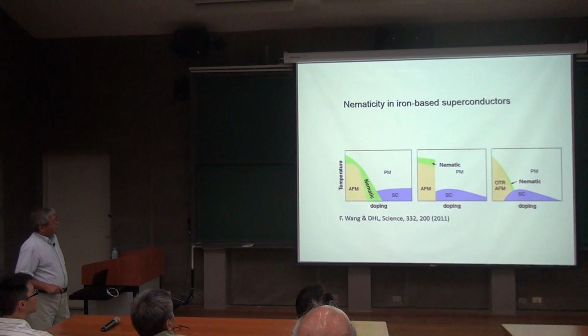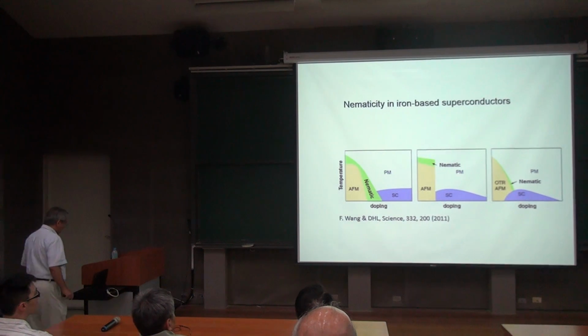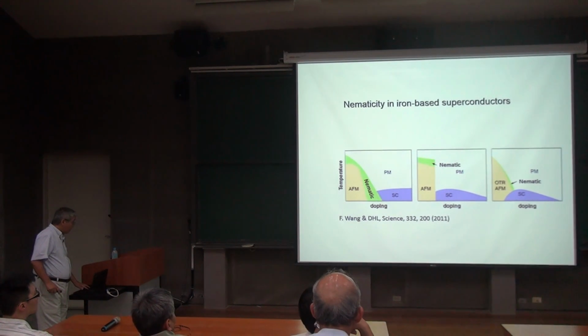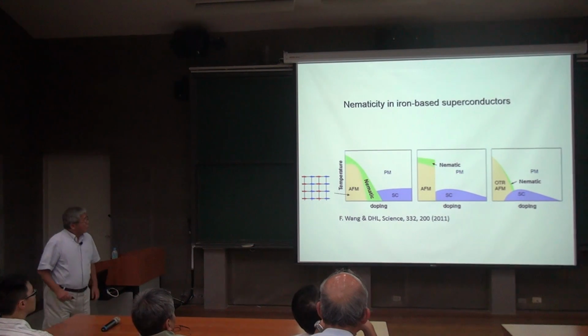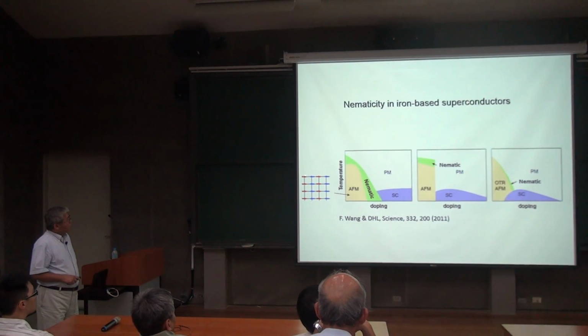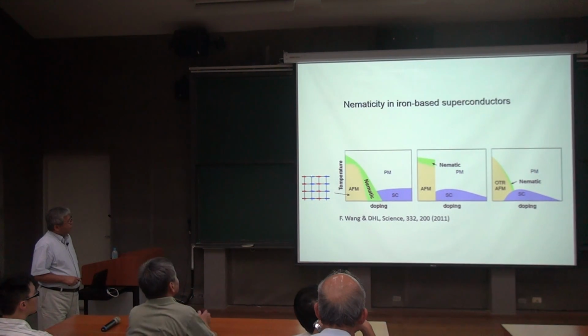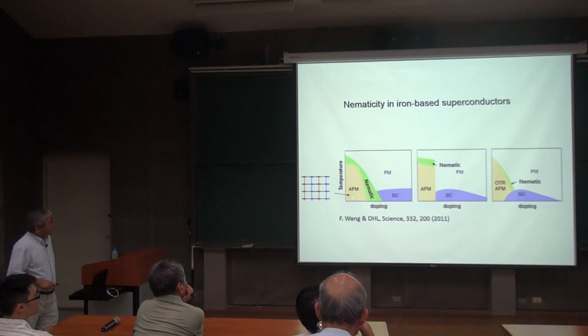a similar phase diagram. If you plot chemical doping versus temperature, the system has a magnetic phase, an antiferromagnetic phase, followed by a nematic phase, and then followed by high temperature superconductivity. So what do I mean by the antiferromagnetic phase? Here, the red and the blue arrows indicate the direction of the local magnetic moment. Unlike the copper oxide high temperature superconductors, this iron-based superconductor has a different magnetic state.